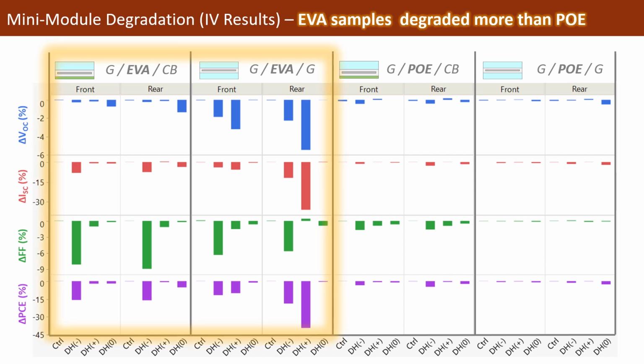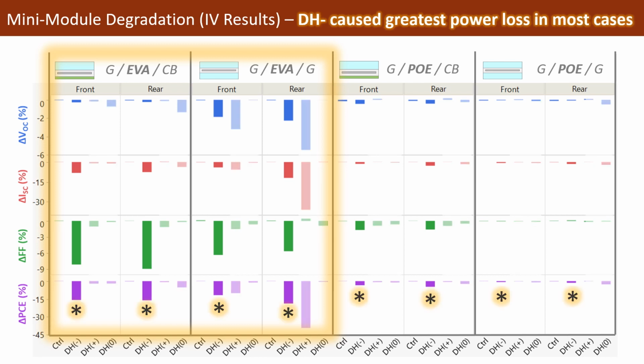The first thing to note is that all samples with EVA encapsulant showed greater degradation than those with POE encapsulant, regardless of whether they were glass-glass or glass-clear backsheet. The most severe degradation was usually associated with damp heat under negative bias, which results in fill factor loss predominantly from shunting in the IV curve.